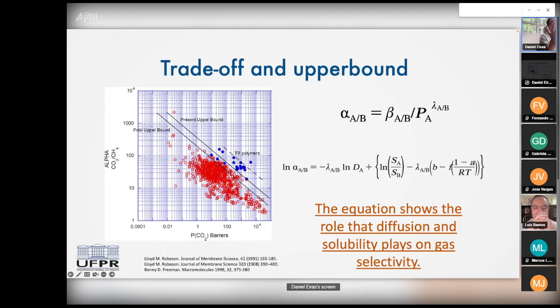So we increase permeability, we decrease selectivity. For example, we can increase this parameter SA divided by SB by introducing specific chemical groups, like ether groups, inside the chemical structure of the membrane. When you do that, we're supposed to increase the selectivity. At the same time, this group increases the flexibility of the membrane and increases the diffusion coefficient, which is going to reduce the selectivity. So bottom line, what we do is try to modify the polymer membrane and deal with this trade-off that is common for polymer membranes.